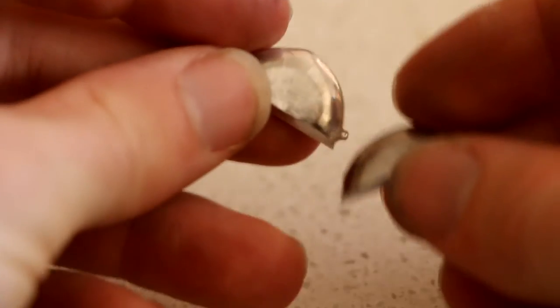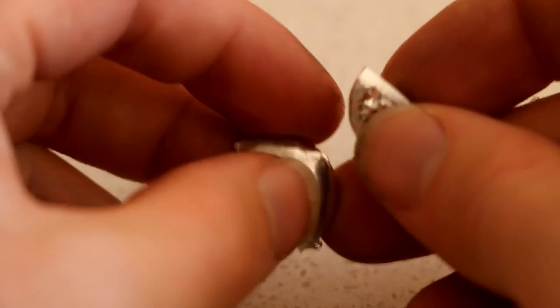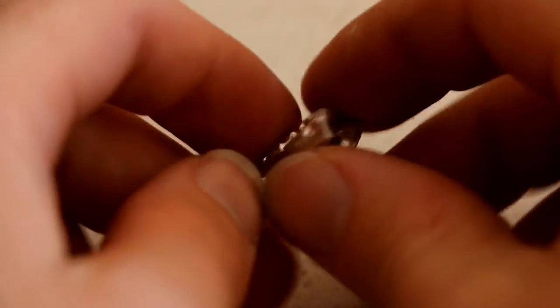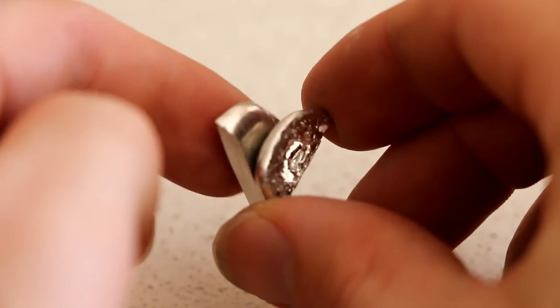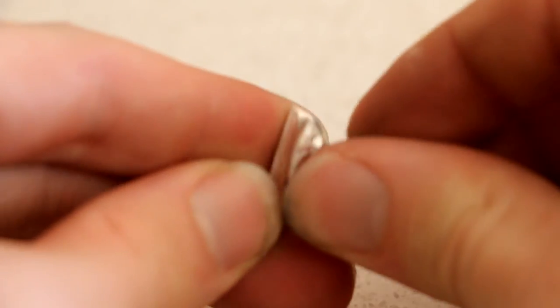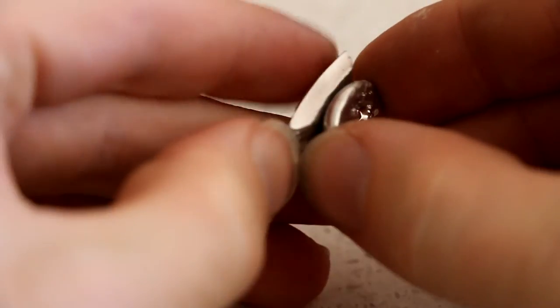Another cool feature about indium is the fact that it is non-reactive in atmosphere, which means it's not going to oxidize and it's going to be a layer of pure indium. So we can do this cool trick — I just grab these, give them a twist. It's called cold welding. By just squeezing out the air between them, the two layers of metal touching each other weld themselves together. I can pull it apart with a little bit of force, but if I get a bigger surface area and twist a bit harder, you can see it's a bit harder to pull apart.